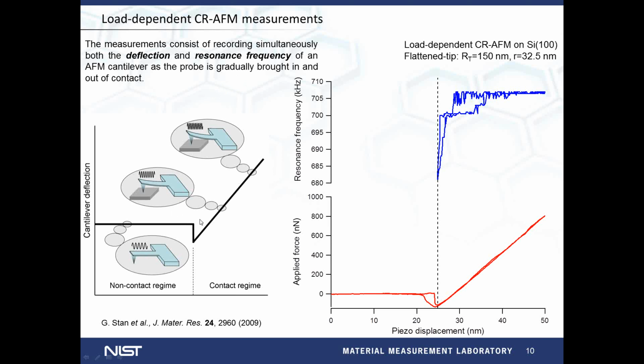And unlike CRFM measurements made at only one applied force, load-dependent CRFM measurements have the benefit of detailing the force or depth dependence of the contact stiffness over the entire contact regions, with a better validation of the involved contact mechanics. Here is an example of such a measurement on a silicon surface, and we observe that the contact resonance frequency remains unchanged once the contact is formed, and this is a clear signature of the flat punch behavior.